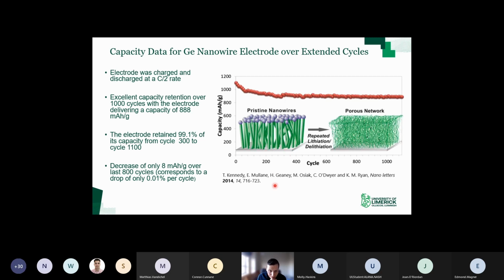So we wanted to look into why they performed so well. So we did some material analysis before and after cycling to investigate what the material looks like afterwards. The prevailing wisdom in the field at the time was that nanowires perform well because they maintain their morphology. So they don't pulverize and they maintain the nanowire morphology. So what we were expecting to see after 1,000 cycles was that we would take apart the cell, wash the material, have a look at it on the SEM or the TEM, and we would still see our nanowires, albeit maybe slightly deformed. And that's not what we saw.